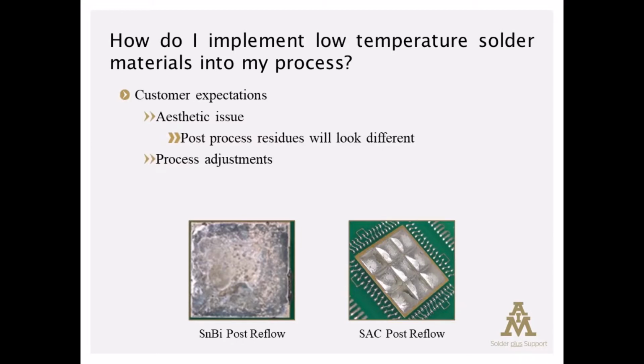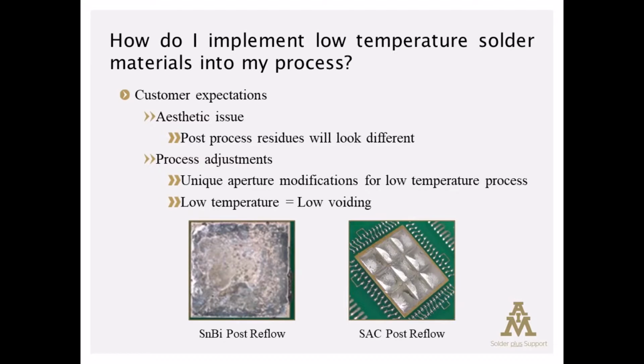There are other things that we're still discovering as low temperature solders get more widely implemented. I expect that the low temperature solders will probably have some sort of aperture modification that will have to take place in order to accommodate the different flow and spread characteristics. They tend to be fairly sluggish wetters. But on the other hand, something we've discovered is that they also tend to be very low voiding. So that's a big benefit. So aside from the reduced warpage, we may also see lower voiding on bottom terminated devices. Lower voiding, less head in pillow defects, which is the driver in most cases for this.